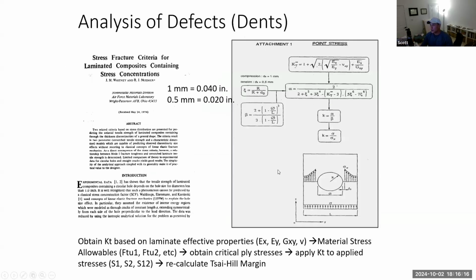Two more slides. So analysis of defects for dents is analyzed very simply. A dent is just analyzed as if it was an actual hole. That's conservative because a dent is not a hole, the material is still there. But from a structural analysis perspective, we want to be conservative, so we analyze it as a hole. There's a paper here called Stress Fracture Criteria for Laminated Composites Containing Stress Concentrations. As you guys are aware, when there are holes, there are going to be stress concentrations occurring near the edge of the holes. And this paper discusses that with equations based off the laminate effective properties, how to calculate the KTs.